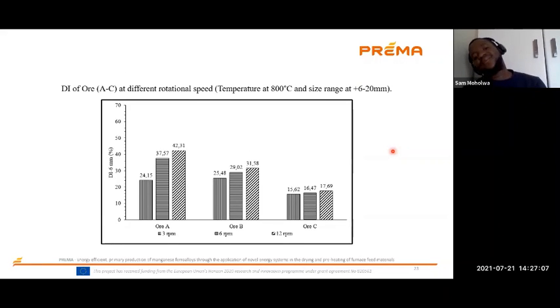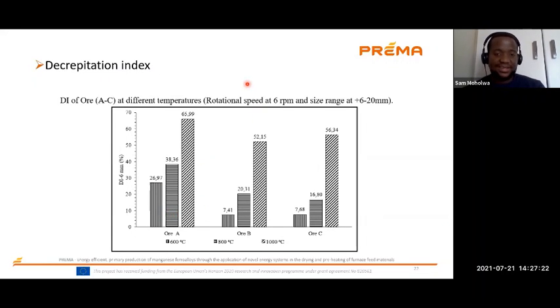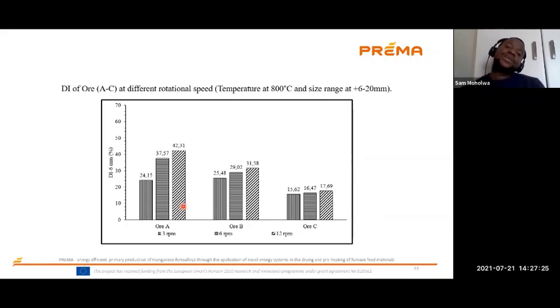Then we go to the effect of rotational speed. As you can see here, the jumps in the effect of rotational speed are not as significant as the jumps that we have seen in the effect of temperature. So rotational speed does have an effect on the DI, but it's not as much as the effect that we experience during the effect of temperature. You can see that it's the same thing, increasing the RPM. We have 3 here, 6 and 12 here. You can see that the DI is increasing, the same applies to OB and OC.